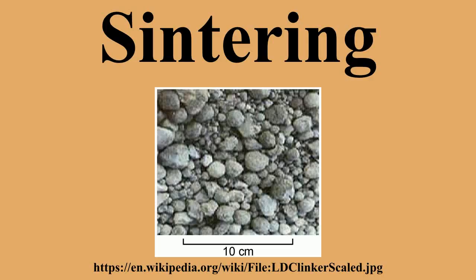For many supported metal catalysts, sintering starts to become a significant effect at temperatures over 500 degrees Celsius. Catalysts that operate at high temperatures, such as the car catalyst, use structural improvements to reduce or prevent sintering. These improvements are in general in the form of a support made from an inert and thermally stable material such as silica, carbon or alumina.